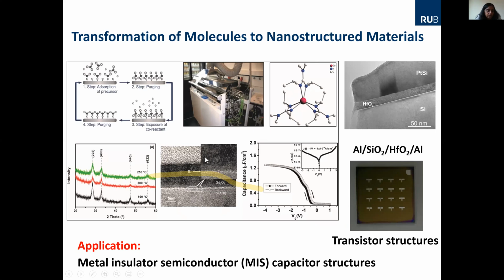And this is a transmission electron microscopy image. And here you can see the X-ray diffraction to show that the films are polycrystalline, and they are actually of a thickness of 10 to 20 nanometers, not much. And together with the engineers, we make the transistor structures where you see, for example, here's an example where we grew hafnium oxide on silicon, and then you have platinum silicide as a top metal electrode. And this transistor structure was built together with the engineers. And here you see the aluminum top contact, then you have the dielectric, the hafnium oxide, and aluminum is a top metal.